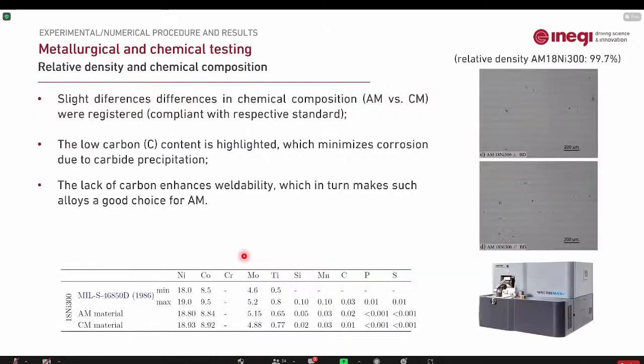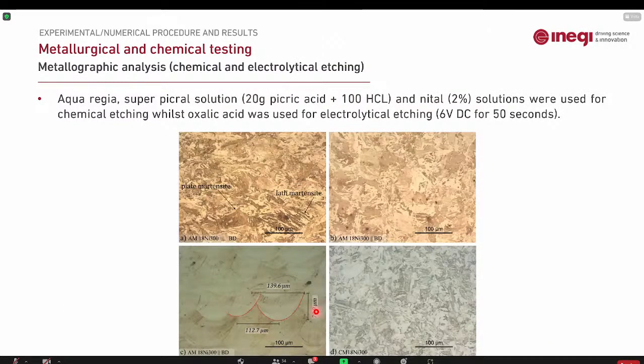We did the typical checking for the sanity of the material. We were very satisfied with the porosity. It is very, very dense. Chemical composition was also compliant with the standards. The micrographs also show the typical morphology of the AM structures, and the conventional is very similar to what is found in the literature.